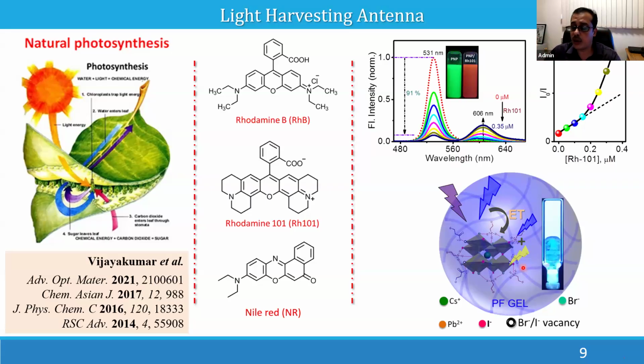In that constrained medium, the nanocrystals are highly stable because these capping ligands cannot move from the tip of the nanocrystal to other areas, and we were able to get very high stability. And by incorporating a very small quantity, even much lesser than the previous quantity, of Nile red, we were able to get a beautiful white emission, because the bluish cyan color is contributed by the nanocrystal, and the yellowish orange color is contributed by the Nile red. Since they are complementary, this bluish cyan and yellowish orange can cover almost the entire visible region. We will see the emission as white.